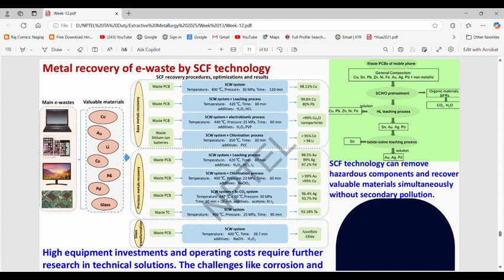Then coming to the glass transformation, waste PCBs can be transformed to glass also with the help of this supercritical water system at a temperature of around 400 degrees Celsius for a time period of around 40 minutes. And the additives are NaOH and some H2O2 that we have to add, and that can convert the polymeric fraction, or we can say the SiO2 fraction present in these waste PCBs, into glass, which is anorthite or albite glass.